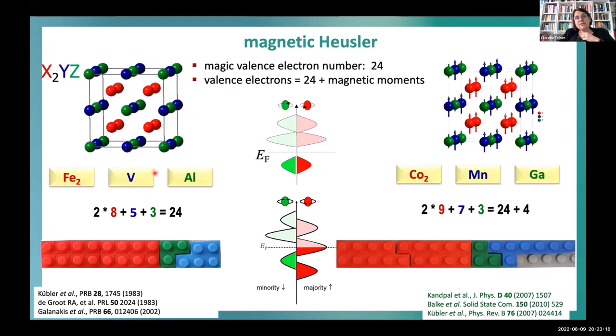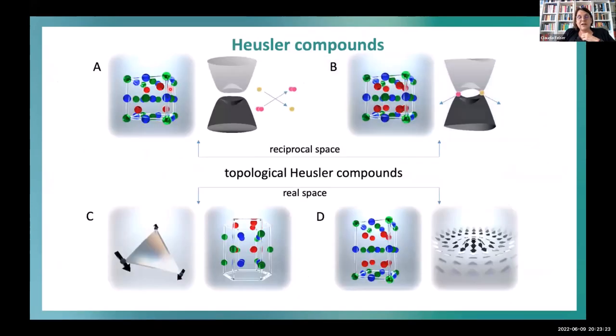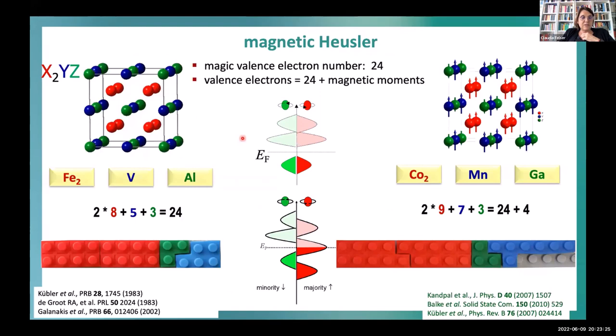So you have certain magic valence electron numbers. You could have read it in this article, sorry, not there, but in the Tanja Graf article, where you really learn about the number counting in this material. We can have the magic numbers 8 and 18 valence electrons. It's like gallium arsenide or mercury telluride. They are non-magnetic semiconductors, but here you can even generate compounds which have 50% iron and two other metals. And then the electronic structure looks like this.